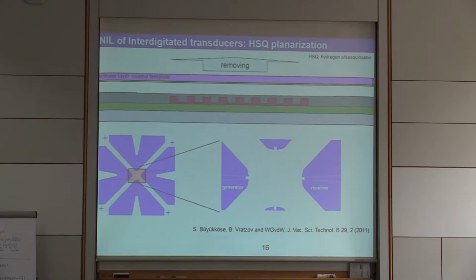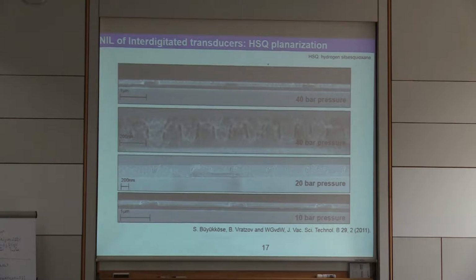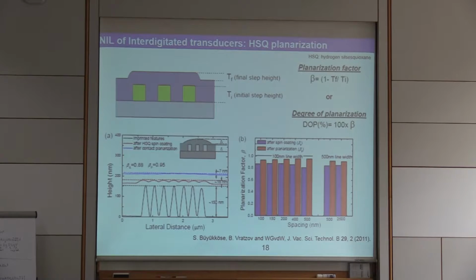So that's why we added this idea of having a flat substrate. So it's basically a double-sided polished wafer that you can push onto this HSQ layer and thereby improve the degree of planarization. And here you see a number of results for different pressures, and probably this gives the best contrast. You see that you really get a very nice planarization there. You have here the organic resist protruding, here this HSQ layer. So now what's the